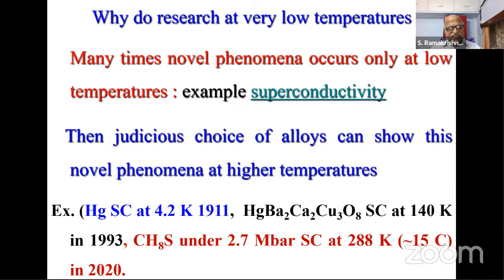So as I told you earlier, mercury was superconducting at 4.2 Kelvin. And in 1993, a high temperature superconductor based on mercury, barium, calcium, copper oxide was superconducting at 140 Kelvin, which is at ambient pressure. Very recently this year, they squeezed hydrogen sulfide coupled with carbon, a CH8S material, at 2.7 megabar. It's a very high pressure. And they achieved superconductivity at 288 Kelvin. Already it is at 15 degrees centigrade.